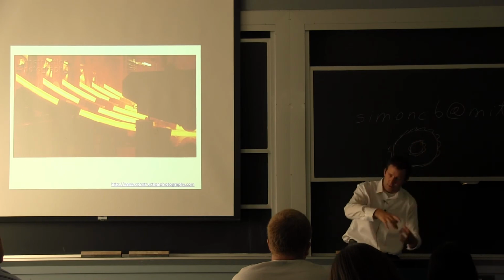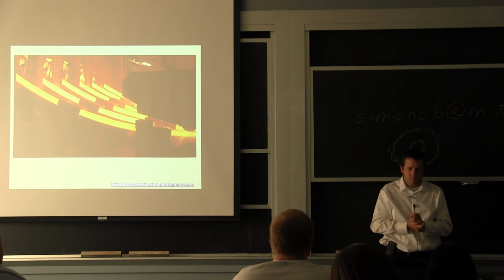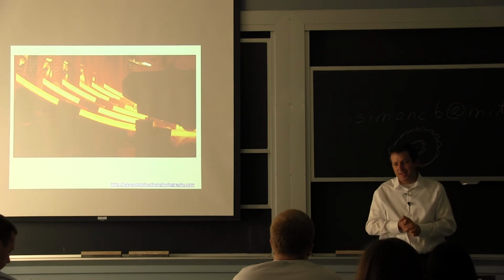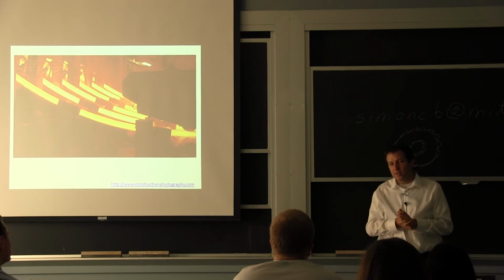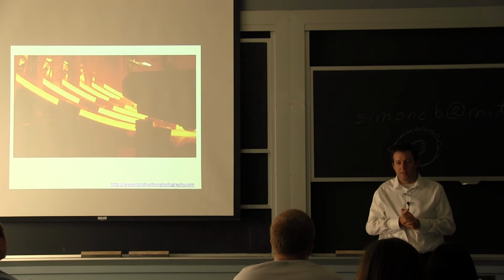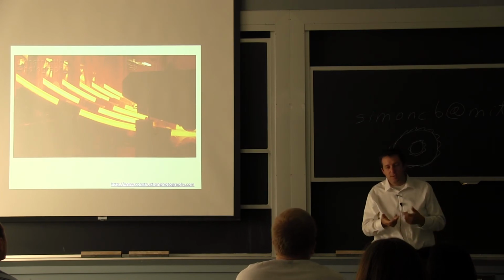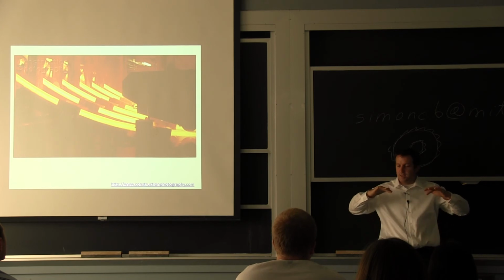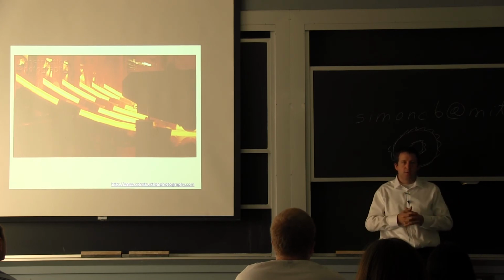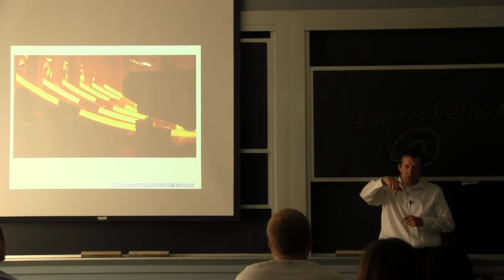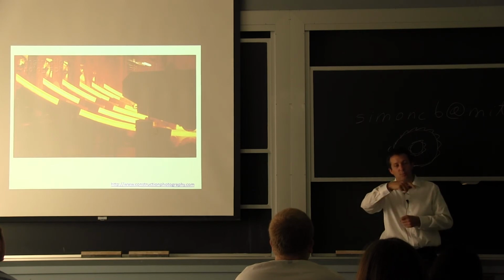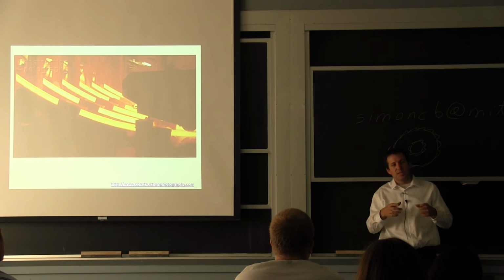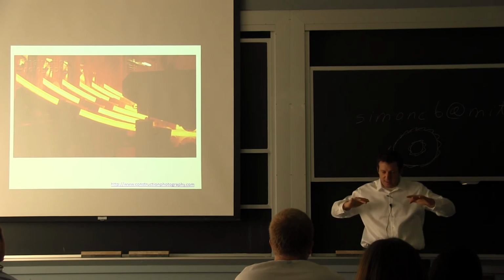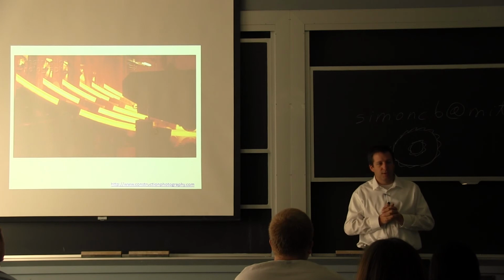Typically it starts vertical, it turns around. And one thing that I wanted, it's a relatively old technology, 100 years type of deal, but at the same time, people still make improvements. So in terms of getting these columnar grains growing, one of the things that was new at the shop that I was at is they were putting on a magnetic field that was strong enough to spin the liquid inside the billet to break these grains, to essentially minimize the finger growth of the metal into the alloy.